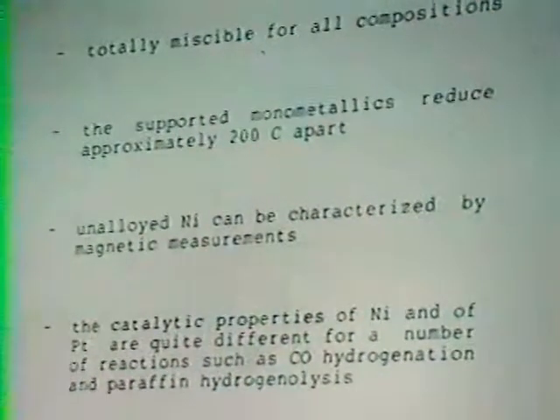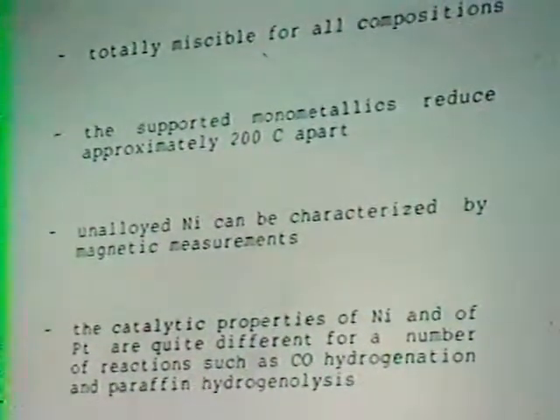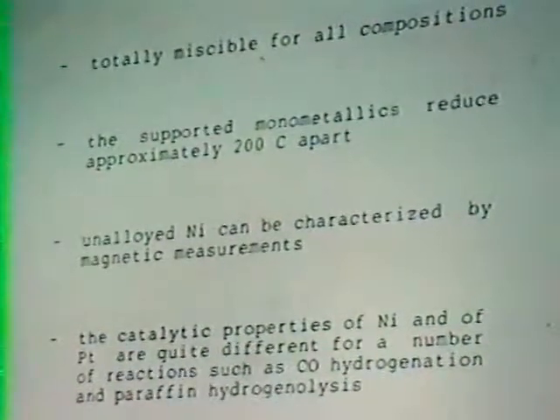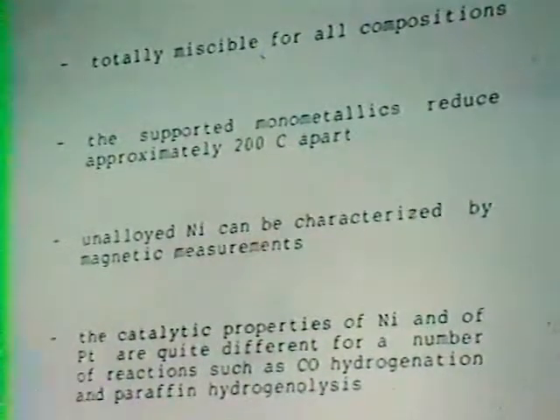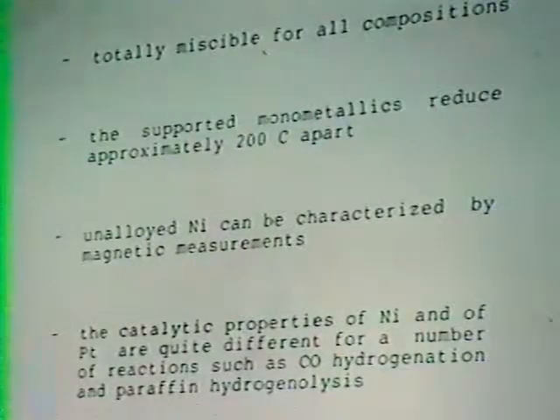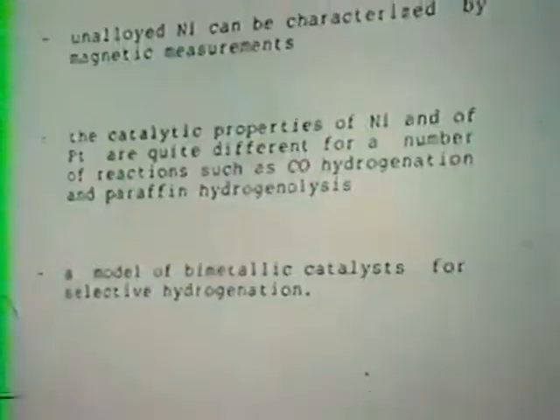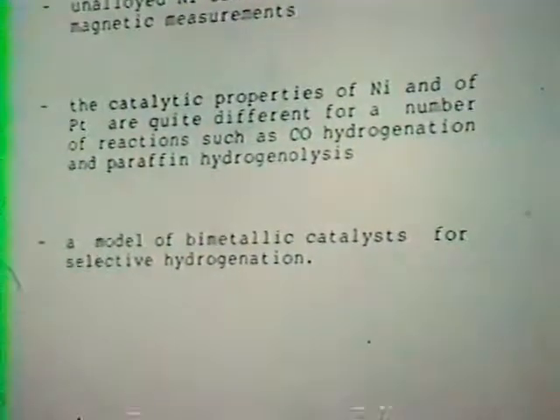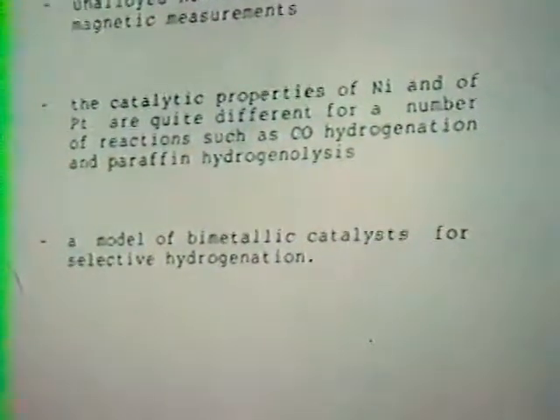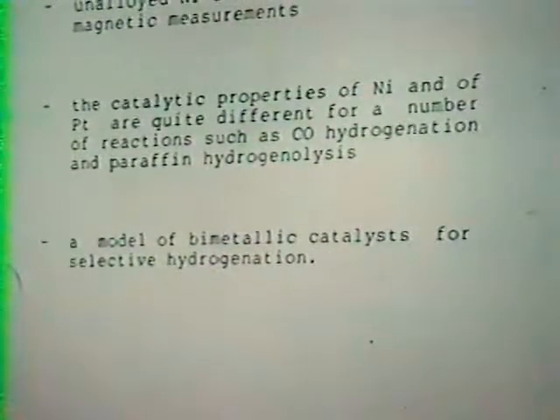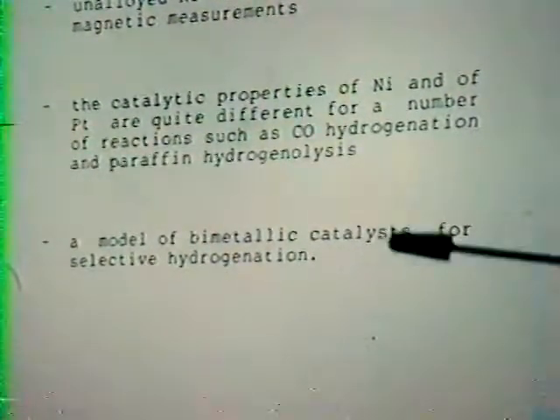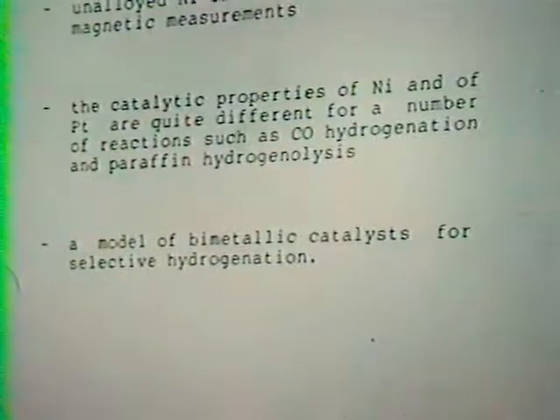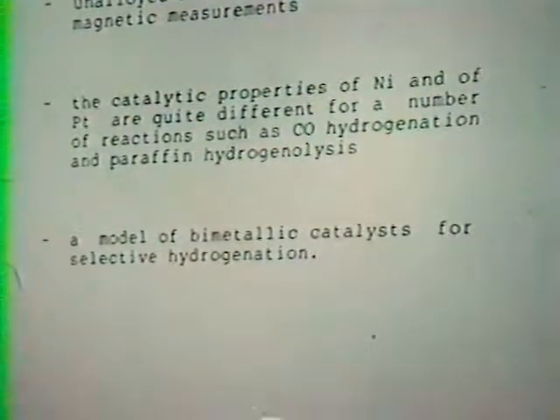Unalloyed nickel can be characterized effectively by magnetic measurements, and if one is investigating the nature of the surface of this bimetallic system, the catalytic properties of pure nickel and pure platinum are quite significantly different vis-a-vis CO hydrogenation, paraffin hydrogenolysis, among other things. And finally, it's certainly an effective model of many bimetallic catalysts for selective hydrogenation.